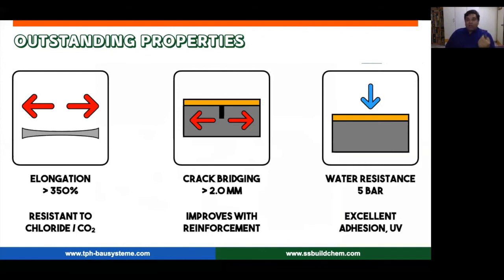Now, the main outstanding properties of these materials is that they have a very high elongation. They're also fiber reinforced, so the elongation comes up to more than about 350-400%. Along with that, this material is so tough, it can actually bridge cracks of almost 2 mm. So if you're laying it onto a well-prepared substrate, then you should not ever have a problem of it opening up again. It's got very good water resistance, about 5 bar water pressure. So you can very easily use it on terraces.